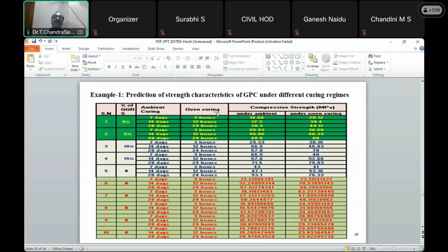What is the effect of temperature on the strength of the concrete? Suppose, for example, you take 70 degrees centigrade, kept constant at 70 degrees. The oven is kept at 70 degrees centigrade, and one concrete specimen cube is cured for 3 hours.